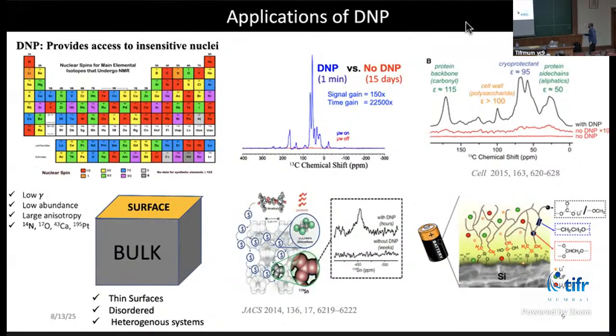So we can boost sensitivity. People have now been able to study cells. We can directly hyperpolarize the constituents of the cell, and then we can boost sensitivity again by orders of magnitude. It's possible to study surfaces. We can selectively hyperpolarize, amplify the signal on the surface and study them. Or you can get NMR signal from constituents which are in very small fraction.